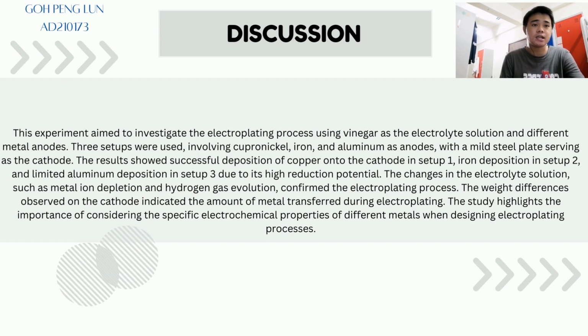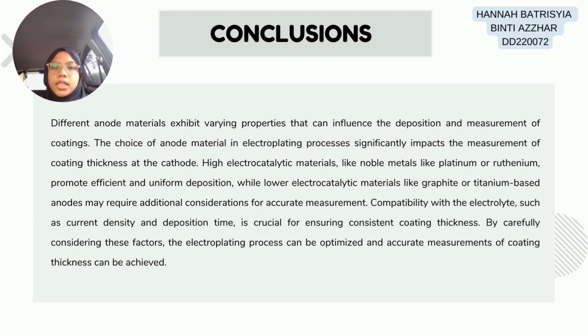Next, the changes in the electrolyte solution, such as the metal ion depletion and the hydrogen gas evolution, confirm the electroplating process. The weight difference observed on the cathode indicated the amount of metal transferred during electroplating. So the study highlights the importance of considering the specific electrochemical properties of different metals when designing the electroplating process. After completing this experiment, we can conclude that different anode materials exhibit varying properties that can influence the deposition and measurement of the coatings.